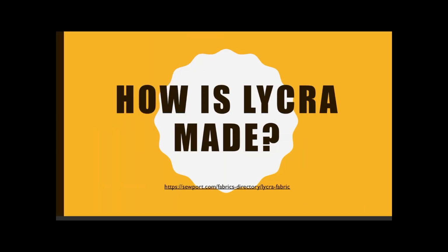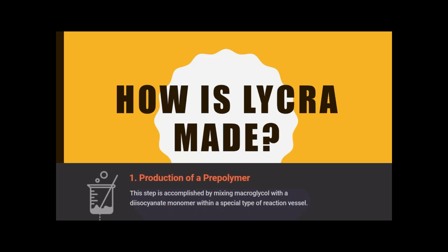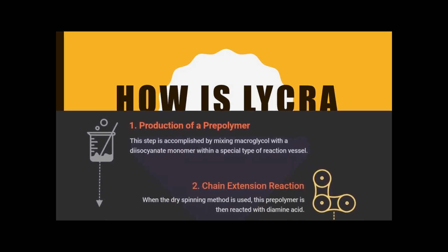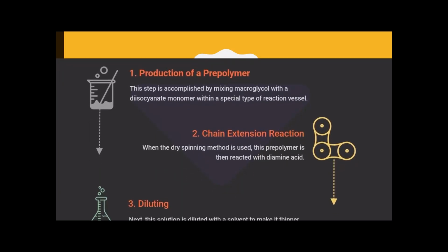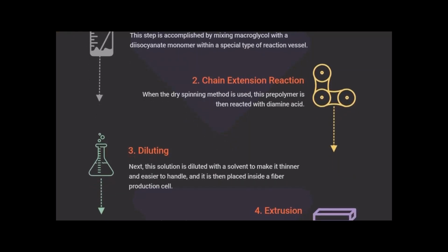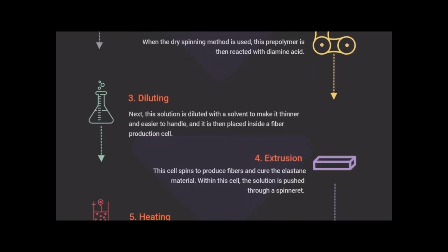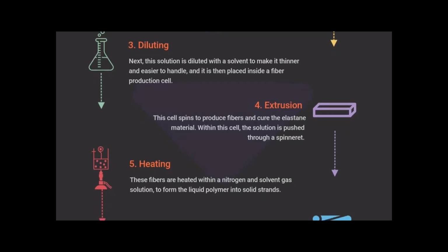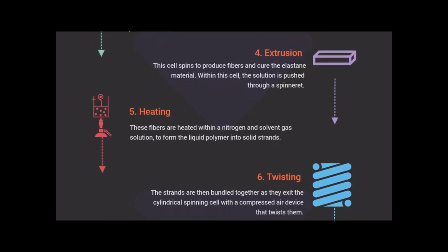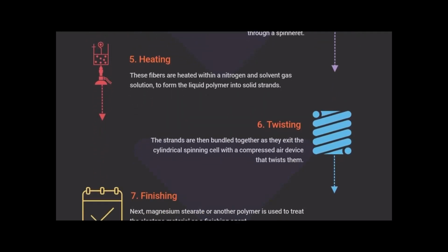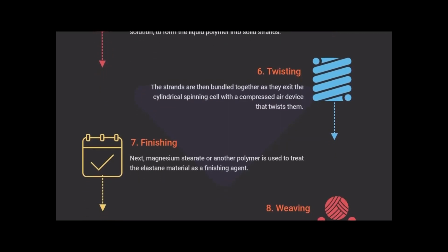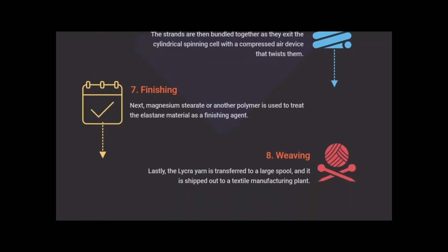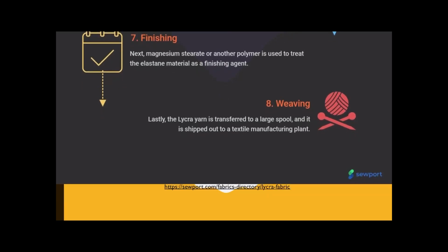How is lycra made? Firstly, you make a pre-polymer by mixing macroglycol with diisocyanate monomer in a special vessel. Then dry spinning occurs and this pre-polymer reacts with diamine acid. The solution is diluted and placed in a fiber production cell. It is spun to produce fibers and cure fibers. It's pushed through a spinneret and the fibers are then heated in nitrogen and solvent gas to form liquid polymer strands. These strands are twisted together and then finished with magnesium stearate as a finishing agent. It's then transferred to a spool and weaved into fabric.